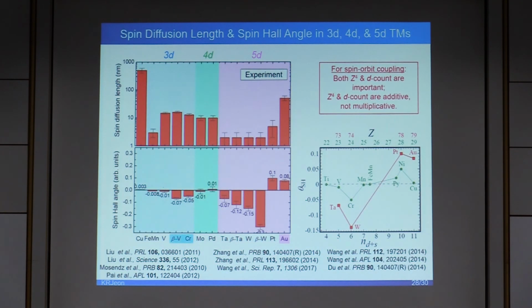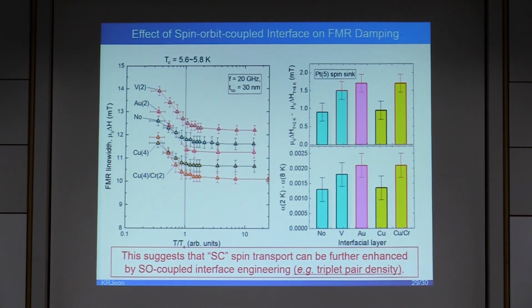Among a variety of materials which are already intensively studied in the field of room temperature spintronics, we have selected vanadium, chromium, and gold because they have a large spin Hall angle, 5 to 8%, and modest spin diffusion length beyond 10 nanometers. Our experimental data showing a further enhancement of FMR damping below TC for vanadium, chromium, or gold inserted samples suggests that superconducting spin current flow can be further enhanced by spin-orbit coupled interface engineering.